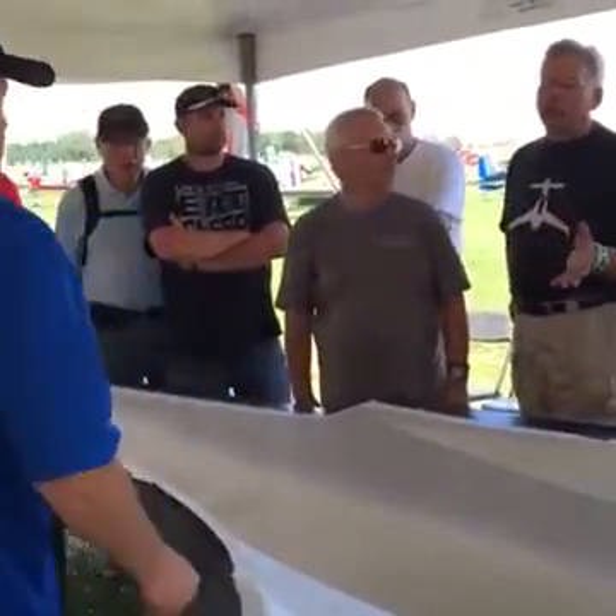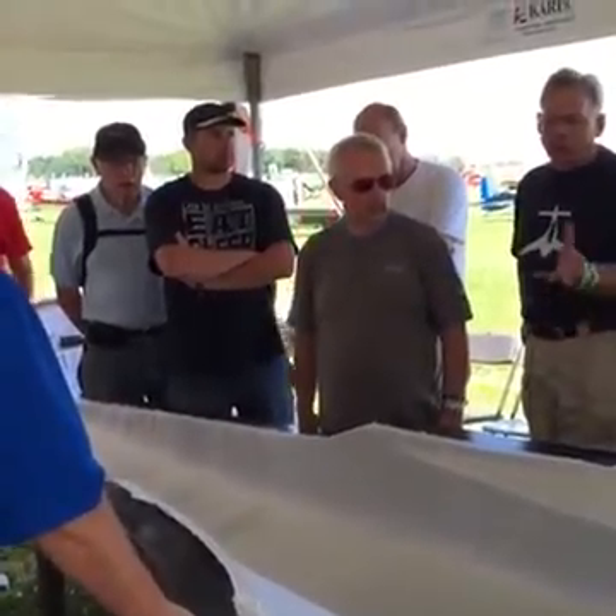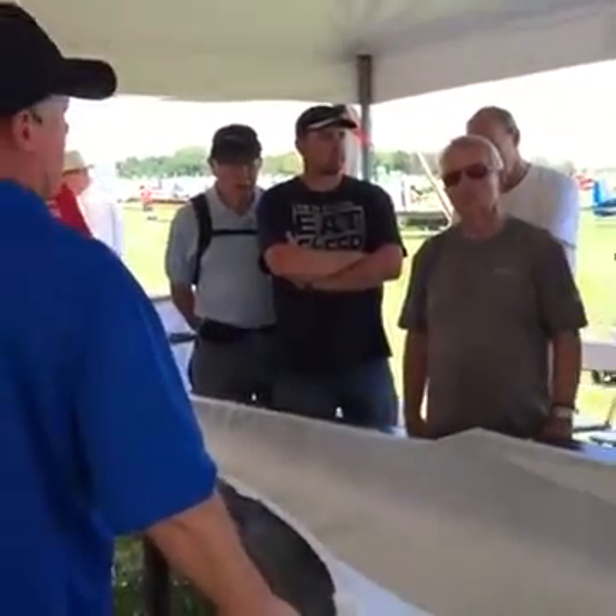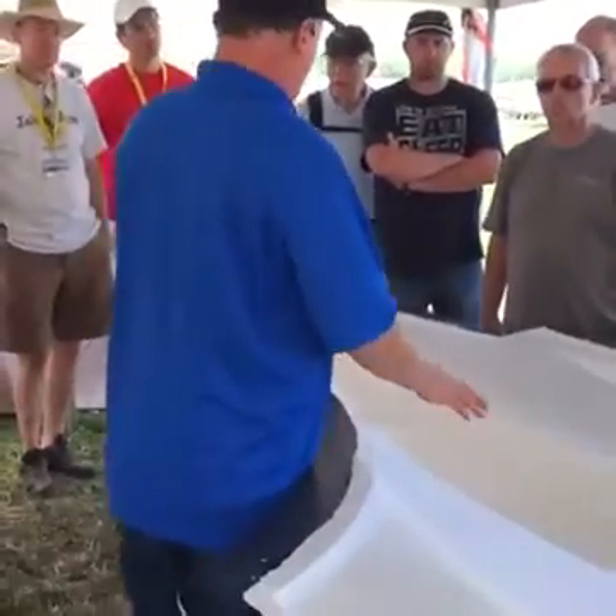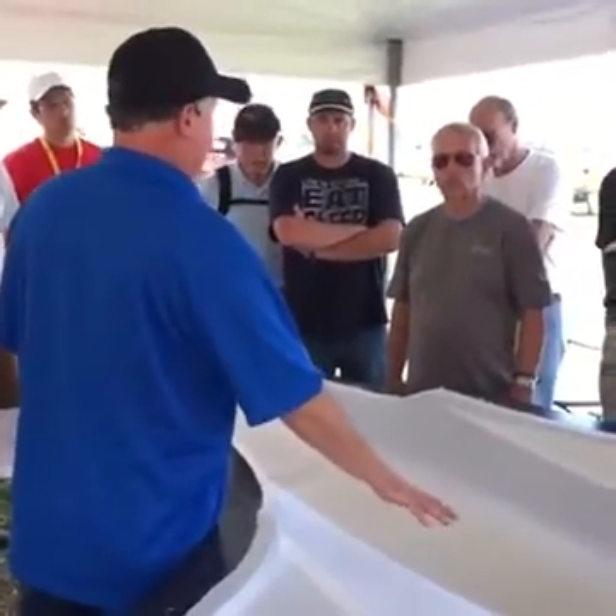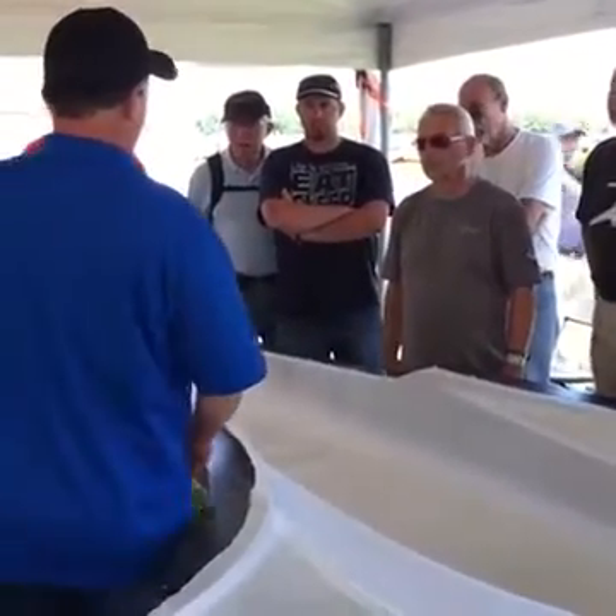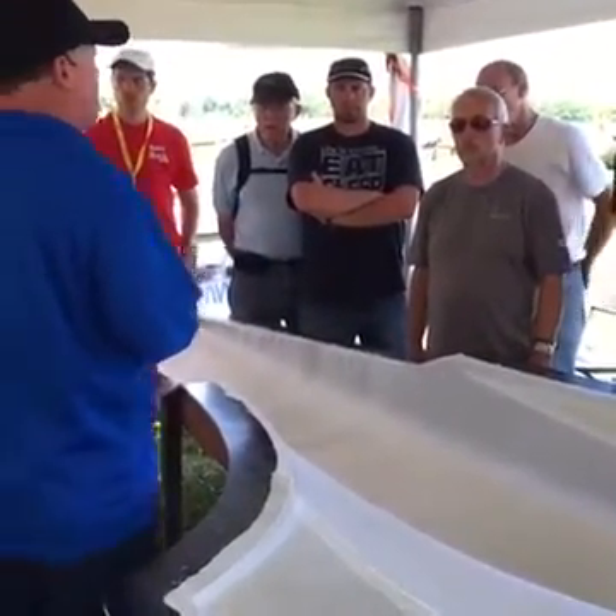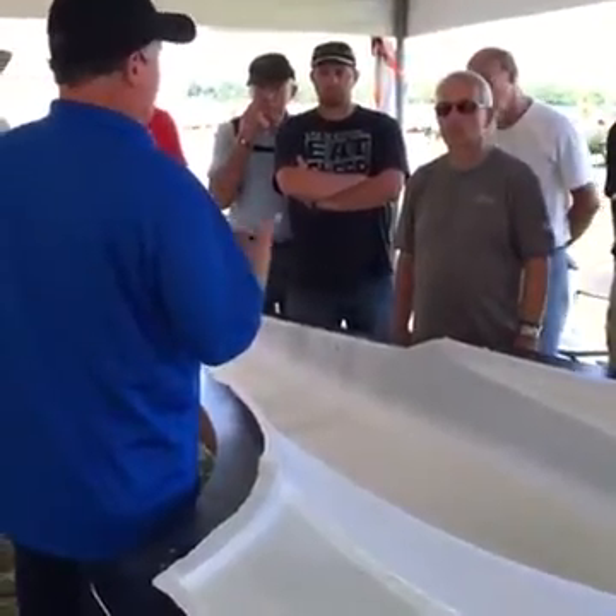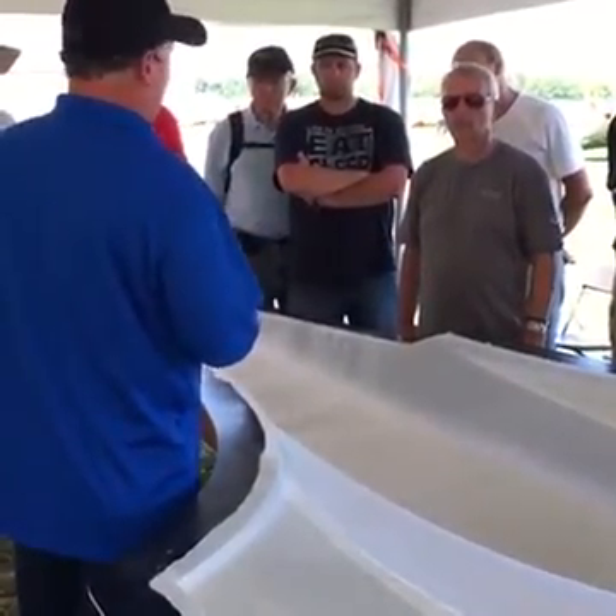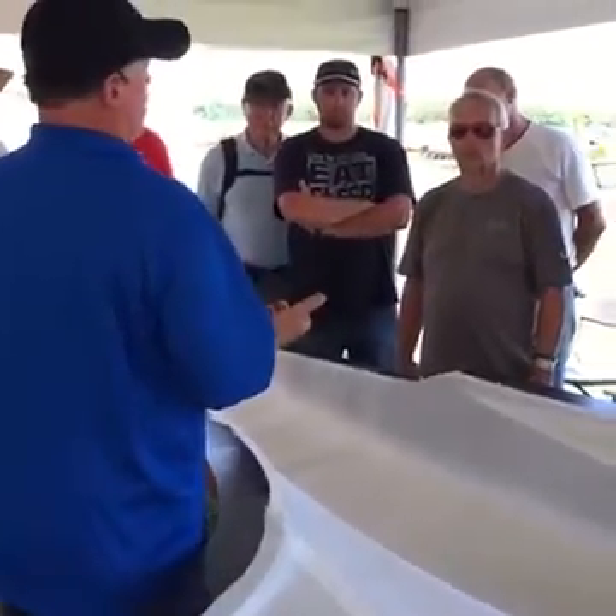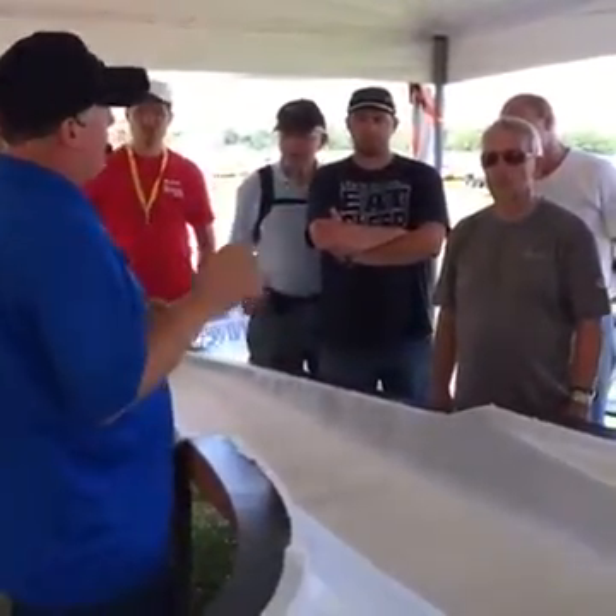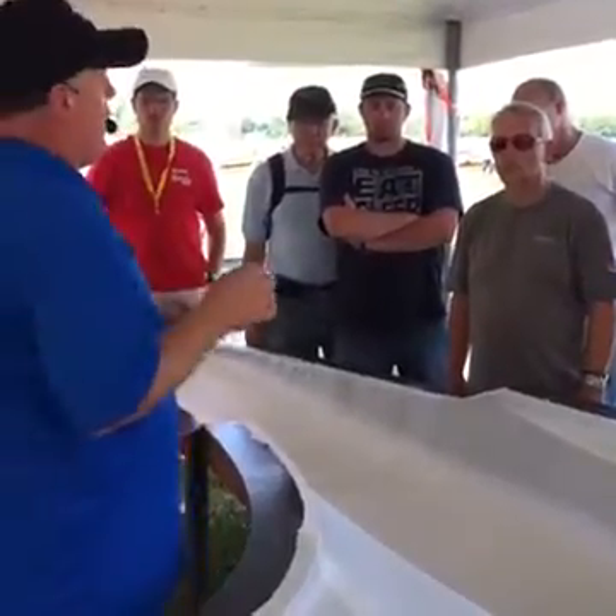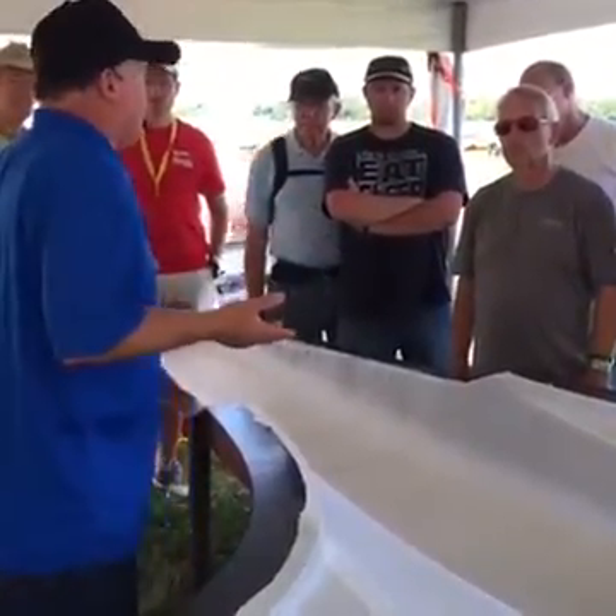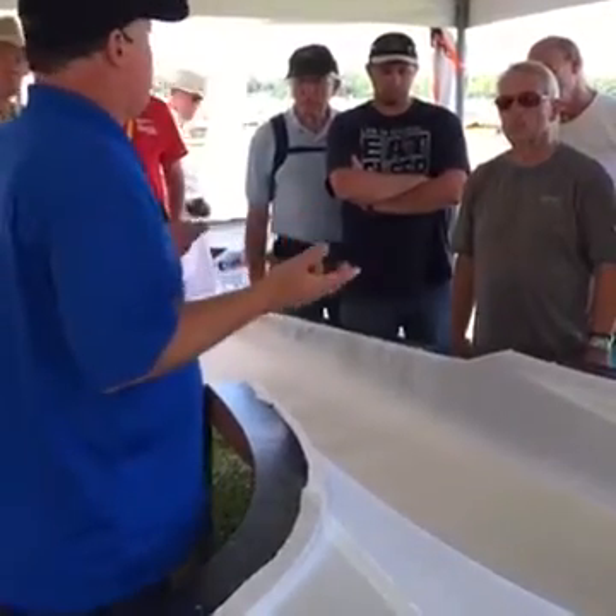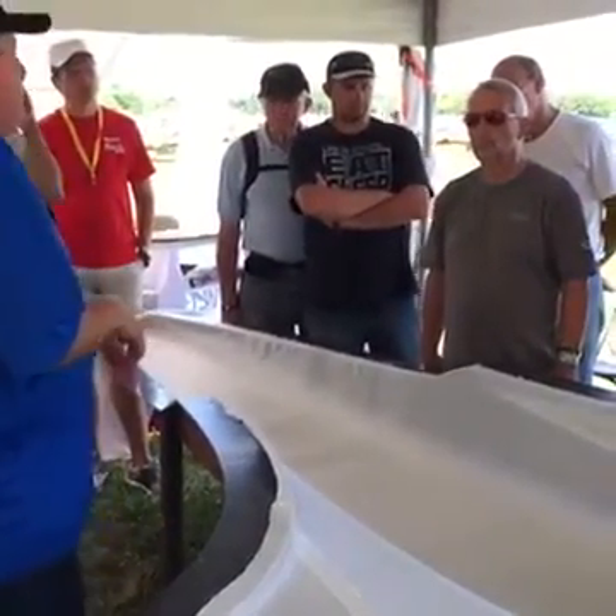The high exotherm and the styrenes that are in it, what are the chances of that getting into the part? On these, there's no styrene that would be in enough of the epoxy. It is a concern, but the resin's only going to lay on top of that part on that mold for about an hour and a half before it gels. And because I'm not going to have any resin mass, I won't have any exotherm to deal with. It's going to be so low. So it's not going to go to that 300? Oh, no.